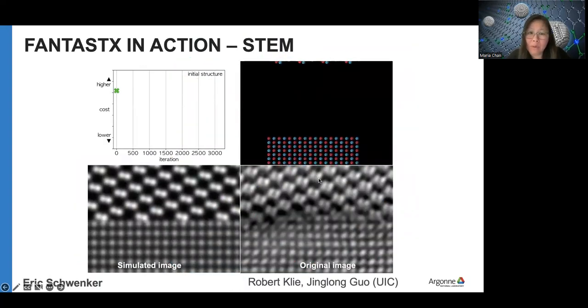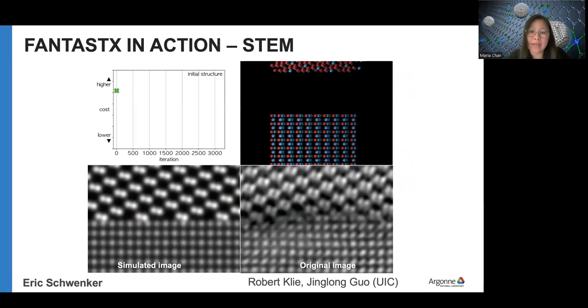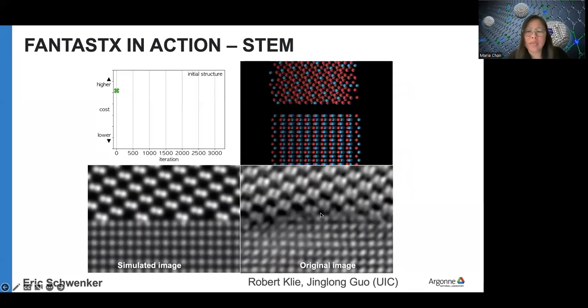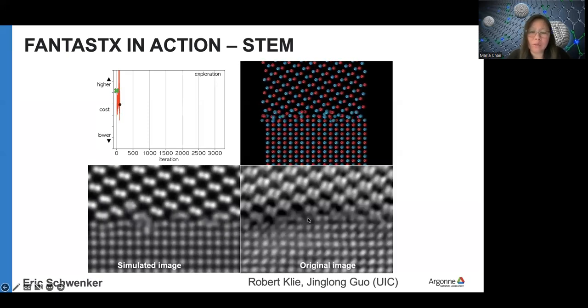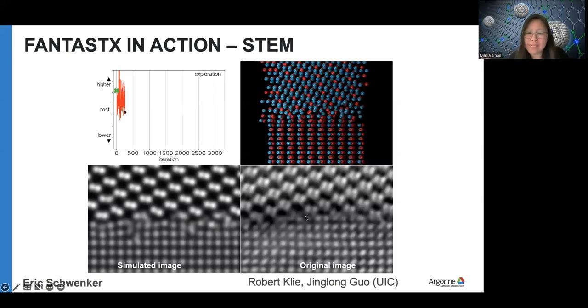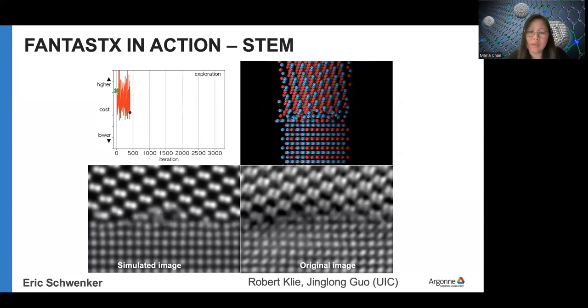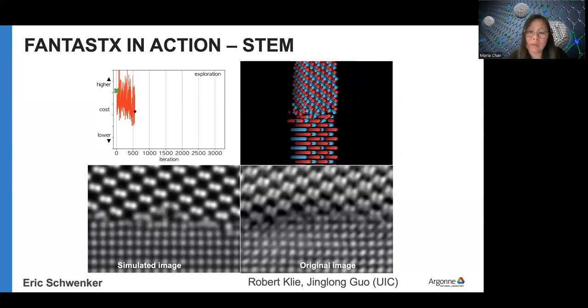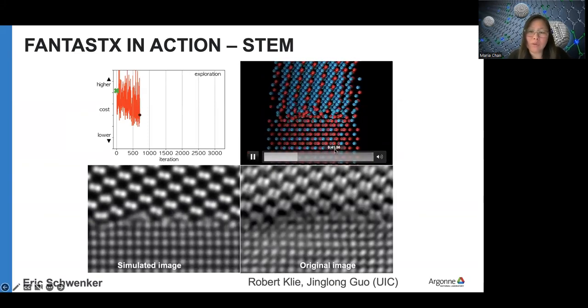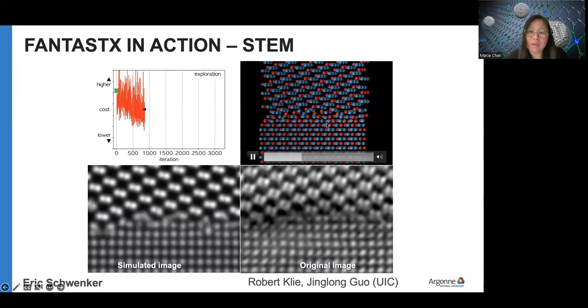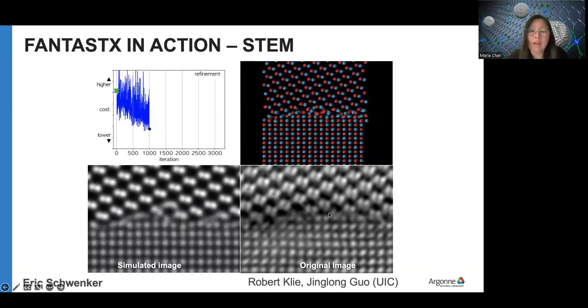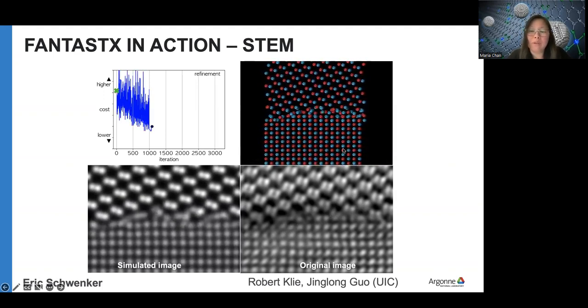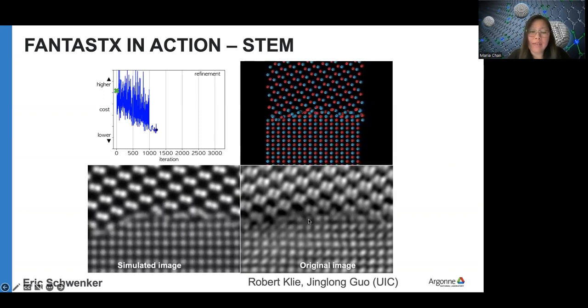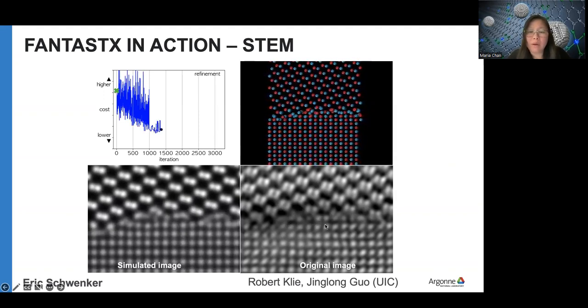And here's an example of FANTASTX in action. It's much easier to see a microscopy example, so that's what we used. It's almost one of the easier problems that FANTASTX deals with, which is turning a 2D TEM image or SEM image into a 3-dimensional structure. So we start with a clean interface that comes out of Ingrain, and then sample the different interfaces, and at each step simulate and carry out a comparison, evaluating the metric of image similarity.